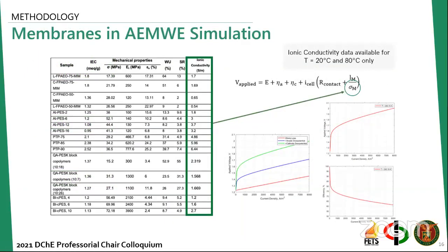Now, for the membranes in AEMWE simulation, please take note that we are to vary the membranes. In order to vary the membranes, we want to check one property of it, which is ionic conductivity. We will be using only this property to vary the membranes. And the ionic conductivity data are available for 20 and 80 degrees Celsius only.